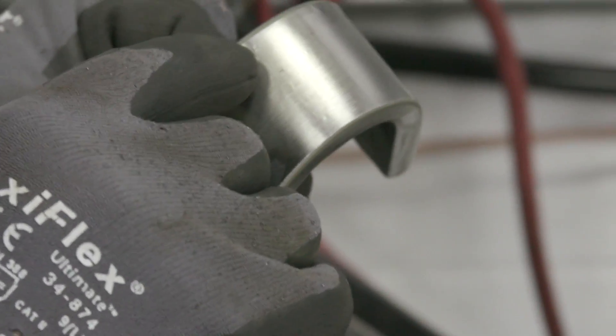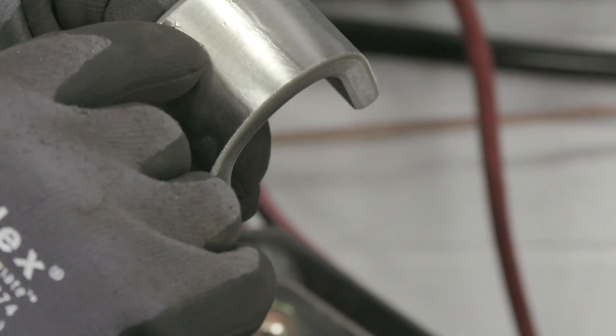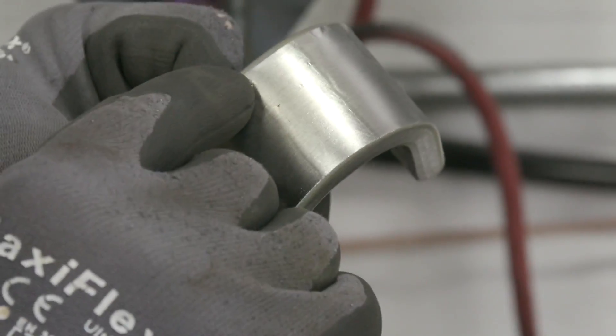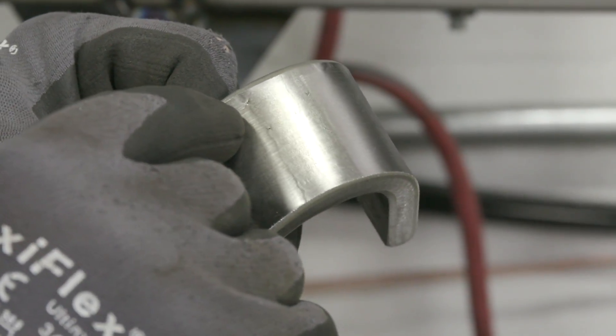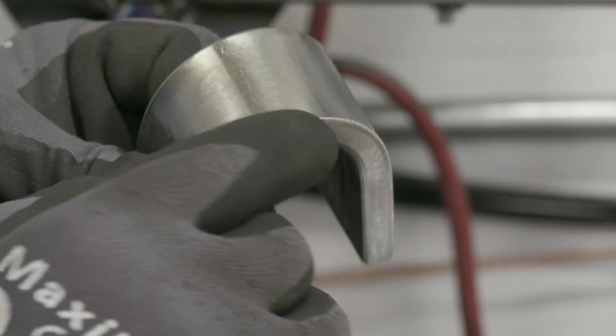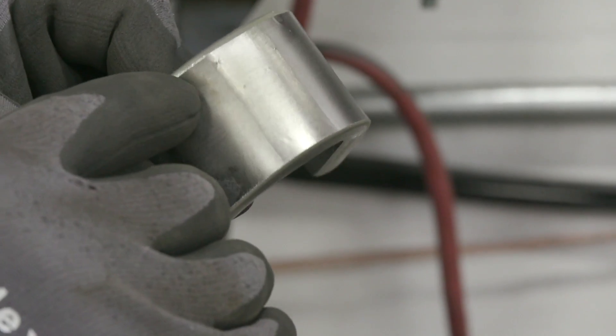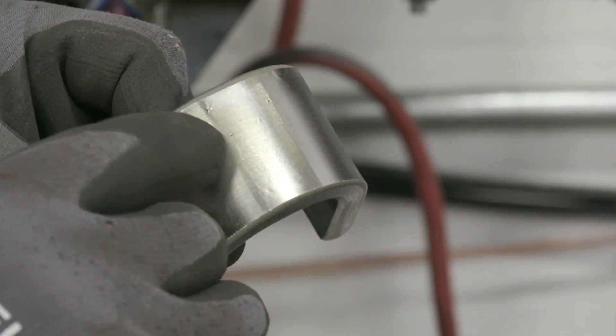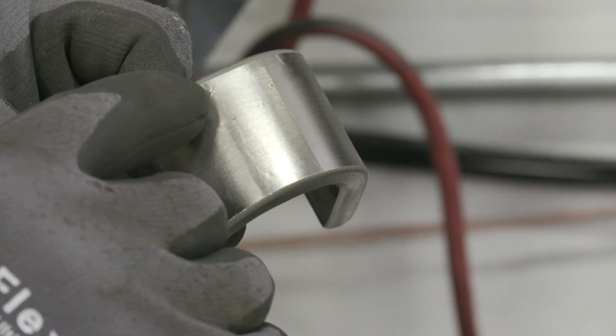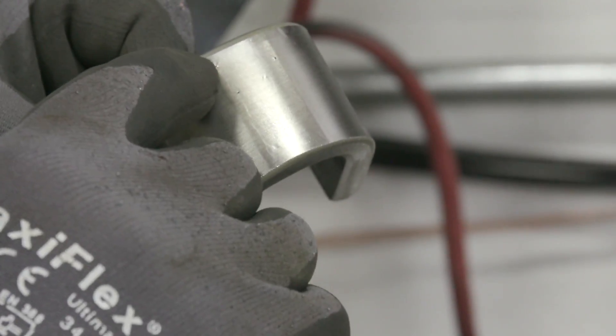We've got three tiny inclusions, one, two, three. All of them smaller than an eighth inch. We'll measure this one because I want to double check the specs on this. I know that they're smaller than an eighth of an inch. Depending on the size, you have to add them up, and then there's a total sum allowed. We'll roll over to the table and we'll get some tools and I'll pull the spec real quick.